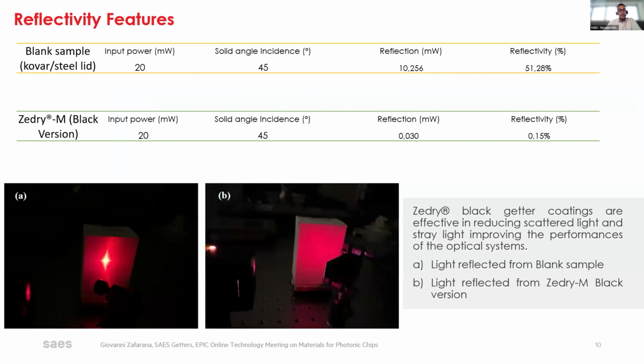Another feature of our products is the reduction of reflectivity. For that, we performed a test with a laser, setting the input power at 20 milliwatts with an incidence angle of 45 degrees, and we measured the reflectivity of the blank sample versus our Zedry-M black version. You can see that the reflectivity dropped from 50% to 0.15%. So this is another result that highlights that we can reduce the scattered and stray light inside the device system and the packages.